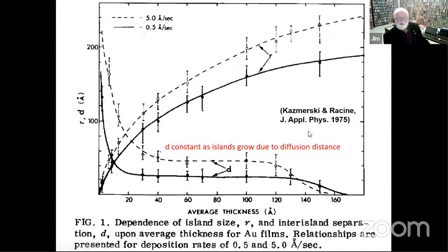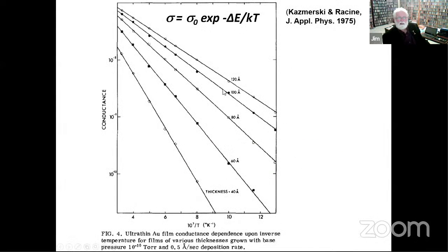So due to the diffusion distance, the separation of these islands is approximately constant as the film grows in thickness. This is at different deposition rates, and so effectively at different substrate temperatures. And these are the plots that I said were of this form. So they look like semiconductors in their properties.